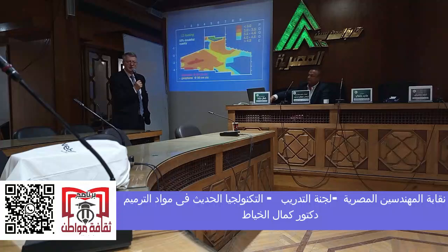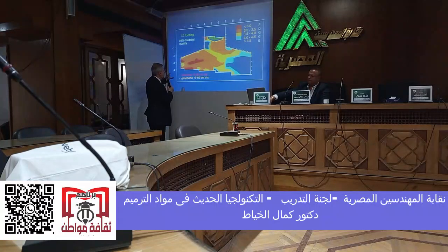I think kilometers per second. That means the quality is excellent. Then the blue is 4 to 4.5, good; yellow is good; orange is deteriorated; red is poor. By the way, this is the side where the river flows, so you have more abrasion and more damage.